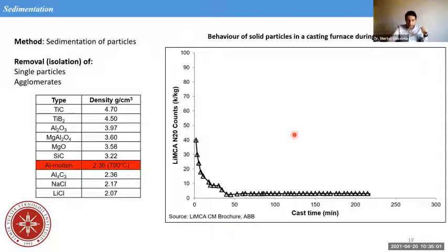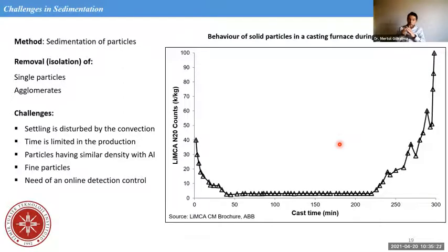And then when the casting starts, it is tiltable furnaces. As you know, we tilt the casting furnace and the melt goes through the launder. So that we have a good inclusion concentration, so good melt quality. And suddenly, when it is close to the end, the inclusion concentration increases. And this is because all the accumulated particles on the bottom are mixed again into the melt. So this is where the casting should stop. And we know it because of the online measurements.